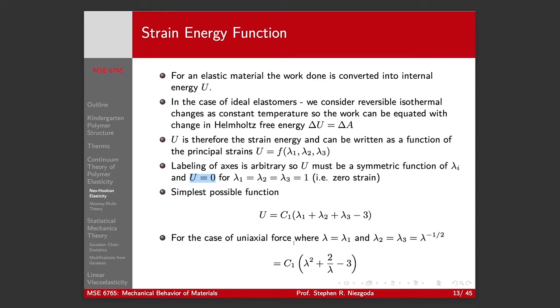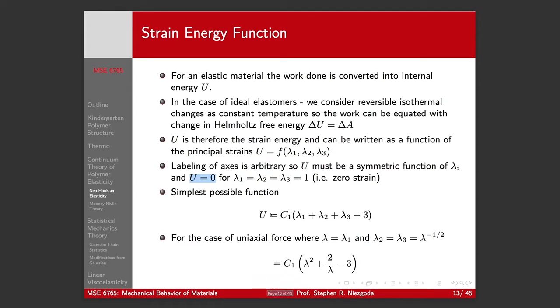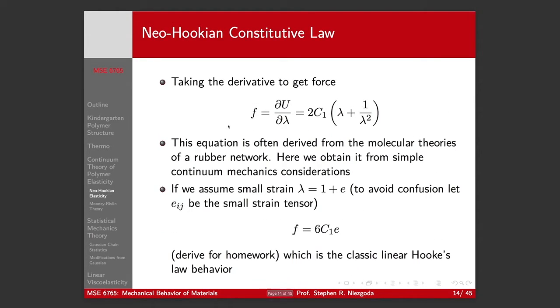Now, let's consider the case of a uniaxial force. And we'll say lambda equals lambda one. We can write, because of our volume conserving lambda two and lambda three, as a function of lambda, and we end up with a form that looks like this. That's our strain energy. So, we take the derivative of that to get the force, and we have a relationship that looks like this.